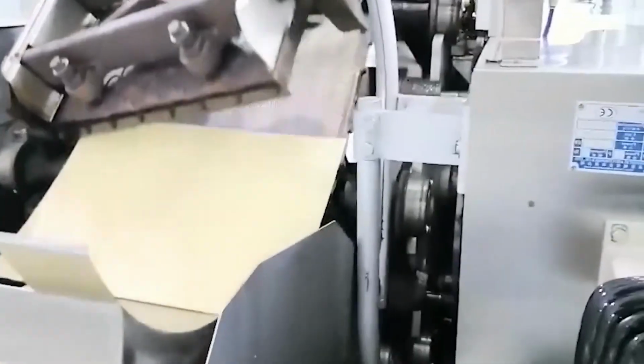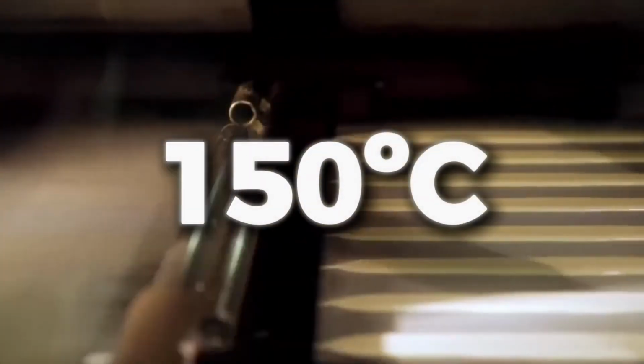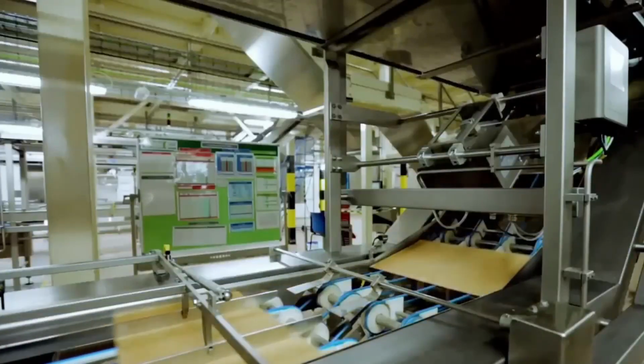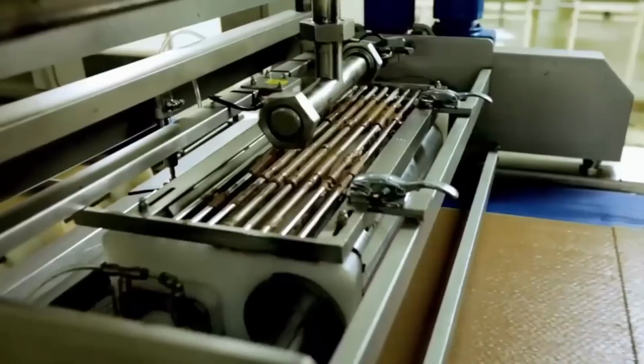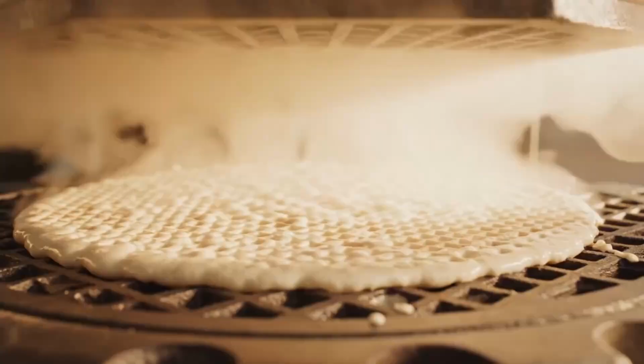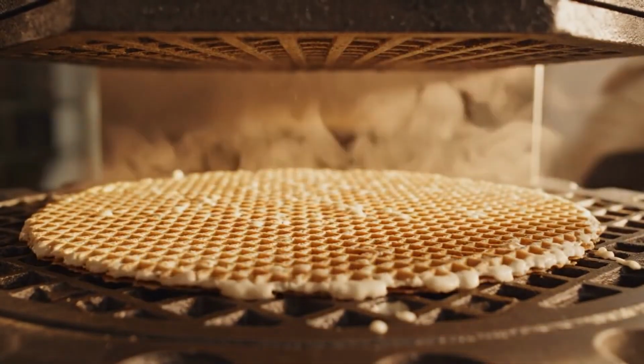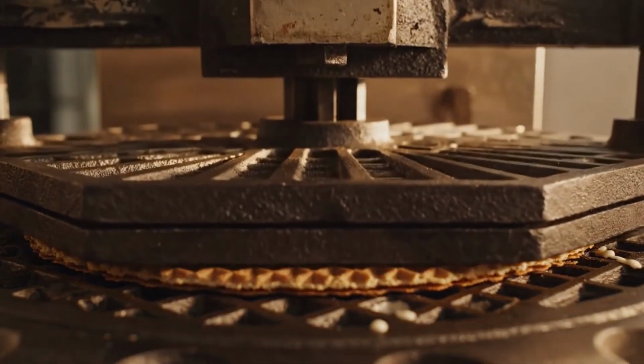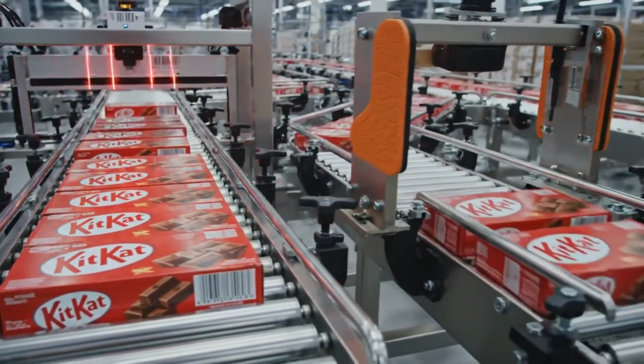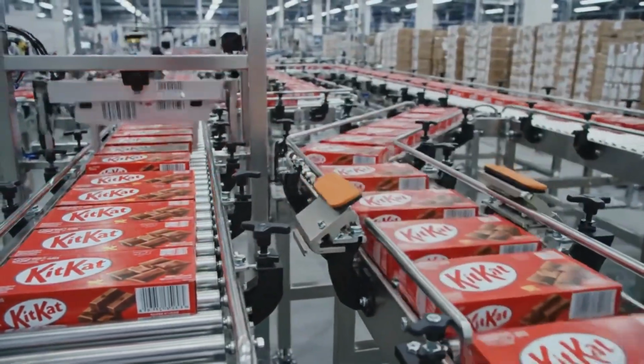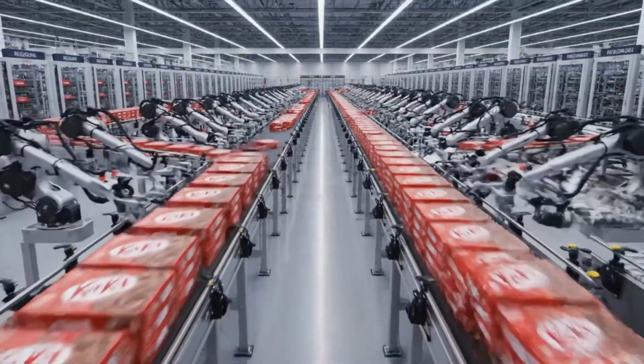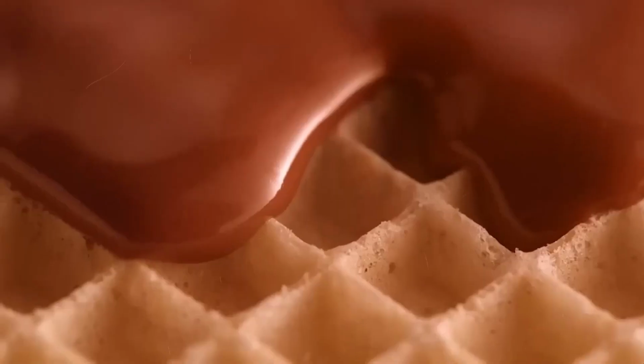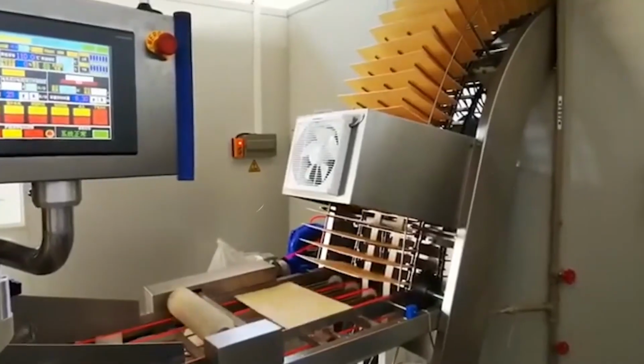The molds pass through a continuous oven operating between 175 degrees Celsius and 205 degrees, 347 degrees to 401 degrees Fahrenheit. Baking time is approximately 30 seconds. In that 30-second window, the leavening agent releases carbon dioxide, creating the internal cellular structure that gives the wafer its characteristic crunch. The surface caramelizes, fixing the texture. Any wafer that exits the oven with a moisture content above 2.5% is too flexible. It will not produce a clean snap and will absorb the chocolate cream filling unevenly.